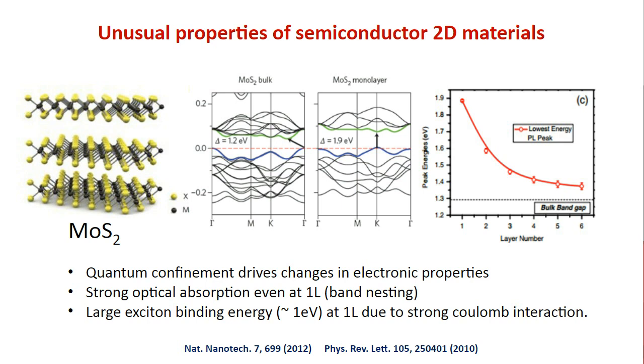Now, MoS2 is not a new material, actually. It is very popularly used as a lubricant because the layers can slide very easily, just like graphene, and it has also some other practical applications and is used in the industry. In the bulk form, which is when you have hundreds and hundreds of layers put together, the band gap is known to be around 1.2 eV, 1.3, which is in the near infrared region. It was first observed in 2010 that when you isolate a single MoS2 layer, the band gap changes from 1.2 eV to about 1.9 eV, which is just about the red part of the visible spectrum.